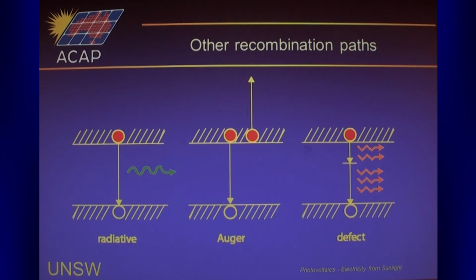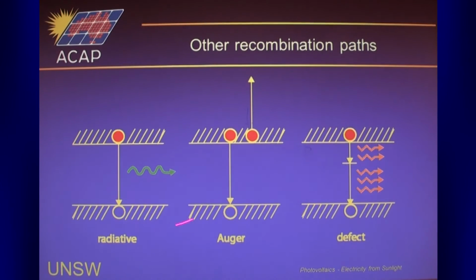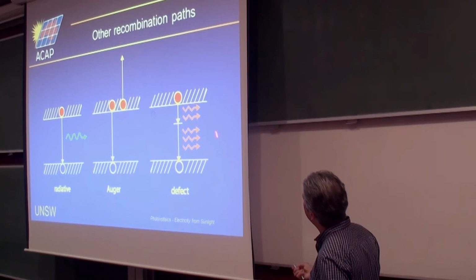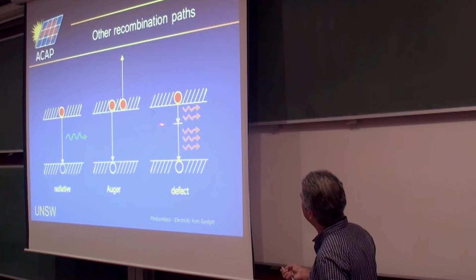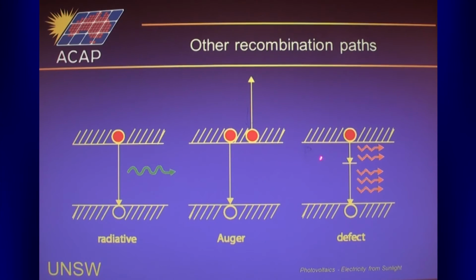But Shockley and Queisser looked at the case where the only recombination processes within the device were radiative. So in our silicon devices, you get a lot of recombination through defects in the material. And this Auger process becomes very critical if you manage to reduce this.